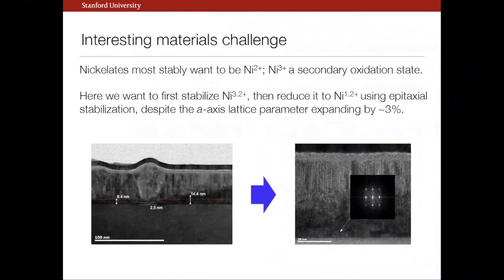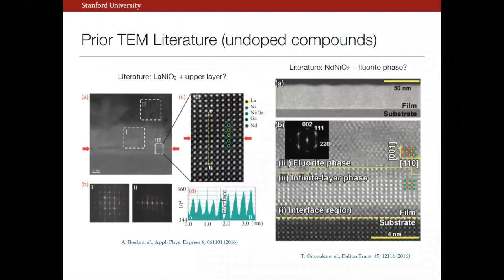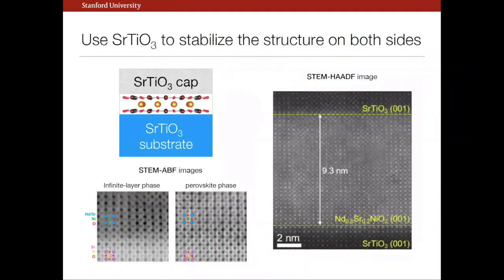The question was why you need a capping layer, and the issue was, well, that after a few nanometers, there's kind of a decomposition reaction above that, and so this is kind of a mess. I mean, now we know that it's fairly low conductivity, and we can kind of separate this out. But the thing of a capping layer is that it normally allows us to be single crystal all the way through the thickness of the film. And so we kind of know what we're studying. And so that's still our preferred mode for things like resistivity or transport in more detail.